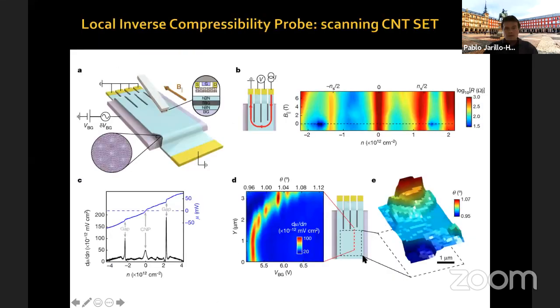So let me show you our data. These are local inverse compressibility measurements performed using a scanning carbon nanotube single electron transistor. So we have a tip which, at the end, is similar to an AFM tip. It has a carbon nanotube, which is acting as a single electron transistor. So it's a very sensitive voltage meter. And we scan this tip above a magic angle graphene sample.